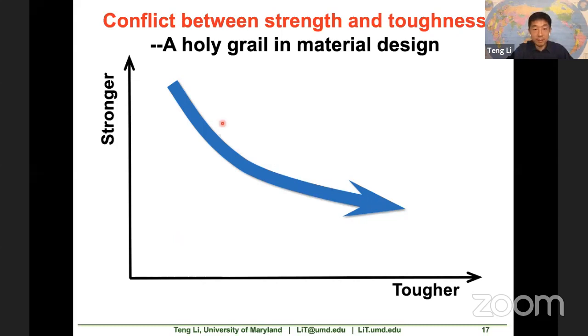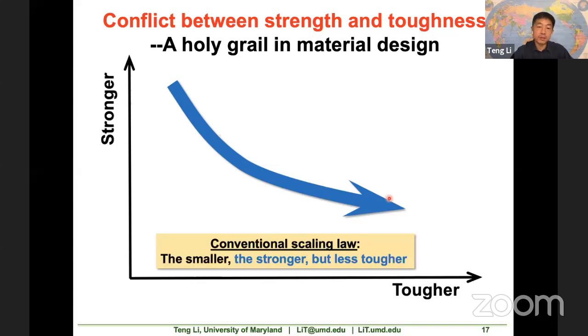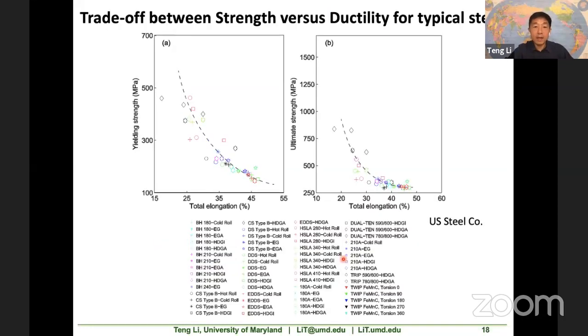So this trend, as indicated by this arrow, is what you see in typical materials. Material scientists have been trying to make materials stronger. One way to do that is to decrease the feature size of the material, like the grain size of a polycrystalline metallic material. You can make the material stronger, but typically at the price of toughness. So it's the smaller, the stronger, but less tough. I use steel as an example. These are the product line of US Steel company. This is the yield strength and ultimate strength as a function of ductility. You can clearly see this decreasing trend: stronger steels have lower ductility, and higher ductility steels have lower strength. And we know that strength and ductility have a strong correlation with toughness. So this corresponds to this decreasing trend between strength and toughness.